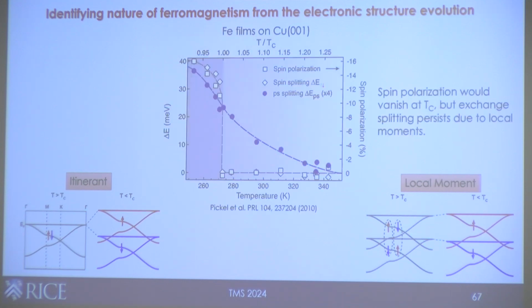So people have used this, for example, to look at iron film, which many think is itinerant. But even for iron film, what you can see in this measurement is that while the spin polarization dies at the ordering temperature, at the Curie temperature, the exchange splitting actually only closes partially, and then persists at a much higher temperature because of the persistence of the local moments, right?